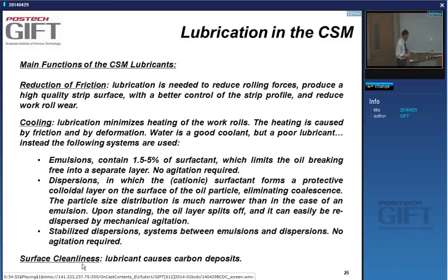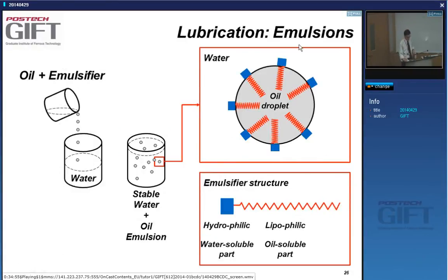Okay. So let's have a look at some basics of the oil-water mixtures that we call emulsions. Yes, so we add oil and emulsifiers. An emulsifier is basically a molecule which has a hydrophilic end and a lipophilic end. The lipophilic end is oil soluble, and the hydrophilic end is water soluble. And so these molecules will orient themselves this way, and this will stabilize our emulsion.